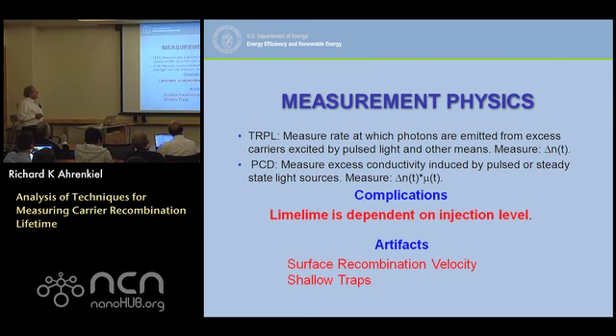The lifetime in things like silicon is related to deep level defects. They're called Shockley-Read-Hall defects, where there's a sequential capture of a minority carrier, then a majority carrier. So it's a defect-mediated lifetime, whereas this is inherently intrinsic unless the material is not good, and then the defects come into play too. So lifetimes are dependent on injection level.